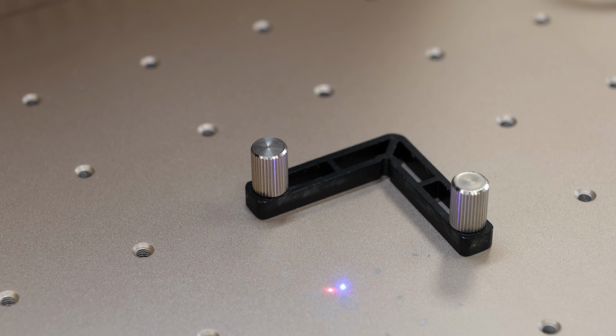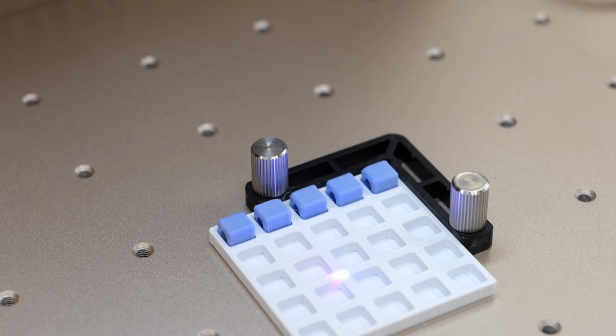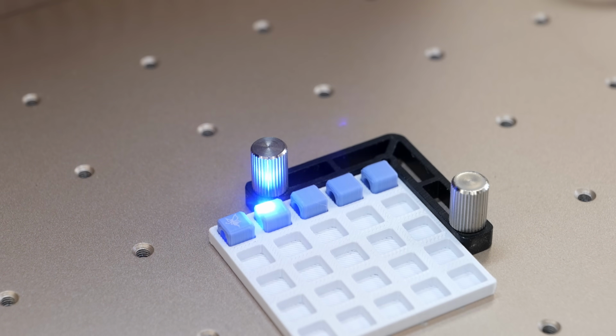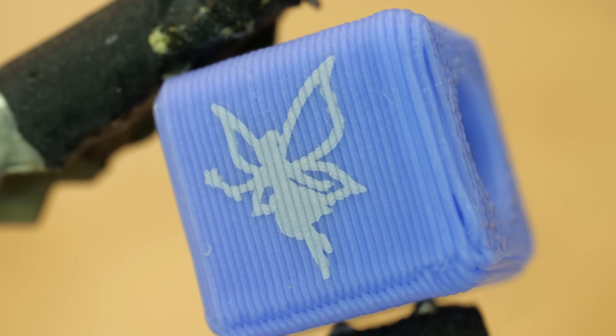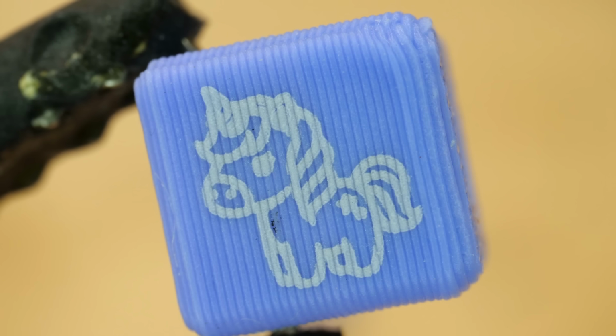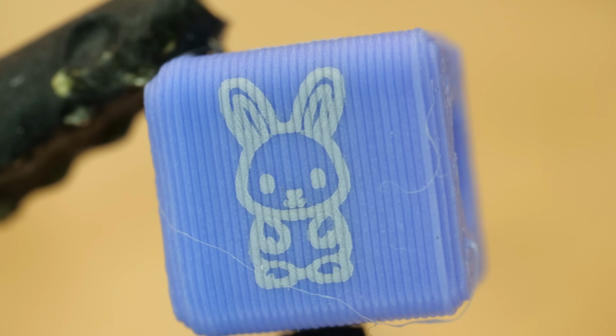I printed the beads themselves from plain PLA, only a few millimeters wide. Then I made a simple fixture that holds the beads in a repeatable position and locates them against a stop inside of the machine. After that, I simply used a setting that had given me the best contrast on the matching sample and engraved different tiny images on the beads. The results were honestly really impressive. At that scale, the small spot size and the precision of the UV laser really shines.